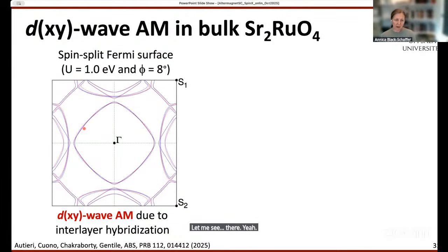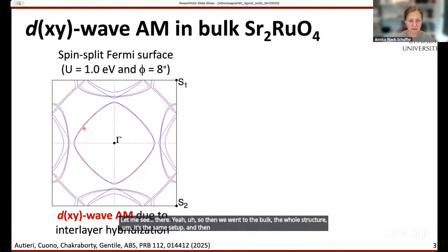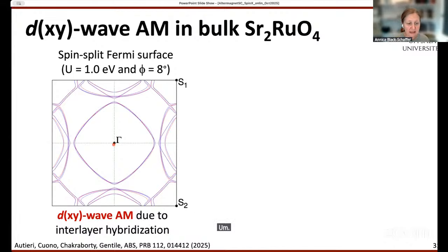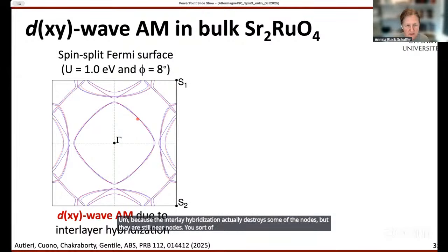So then we went to the bulk, the whole structure with the same setup. And then it turns out that you end up with a d-wave structure here because the interlayer hybridization destroys some of the nodes, but they are still near nodes. You see that there is less spin splitting here, but technically there is some spin splitting there.